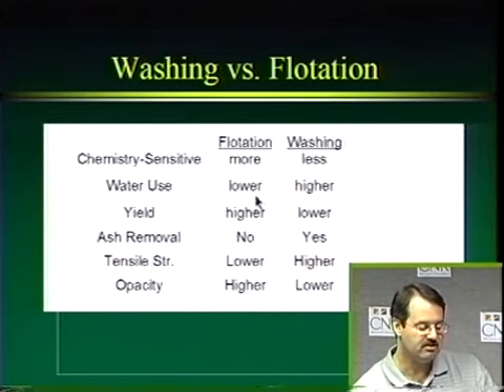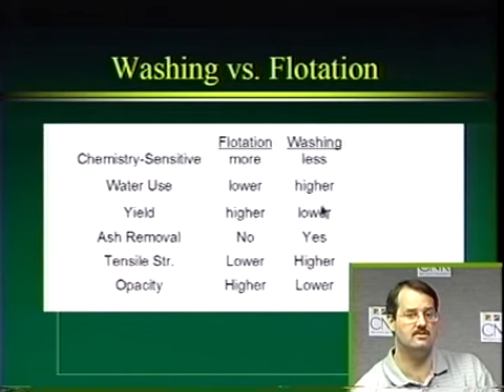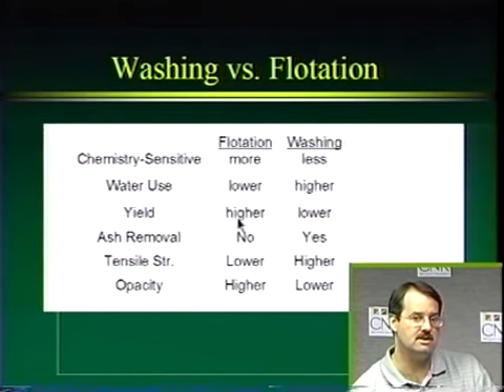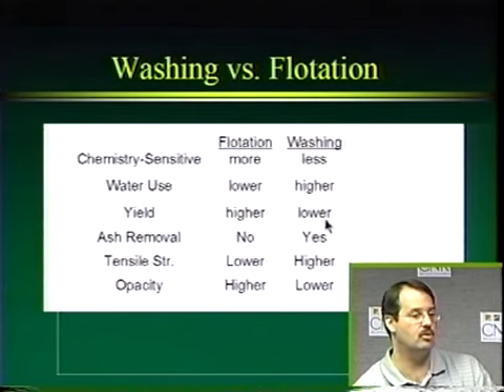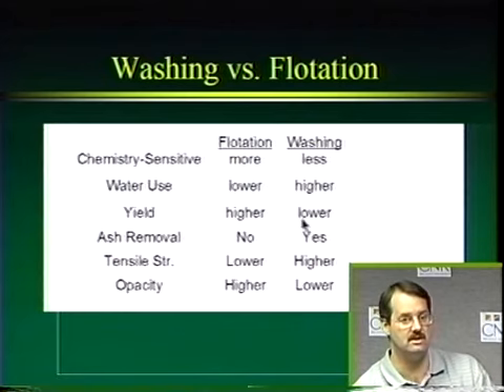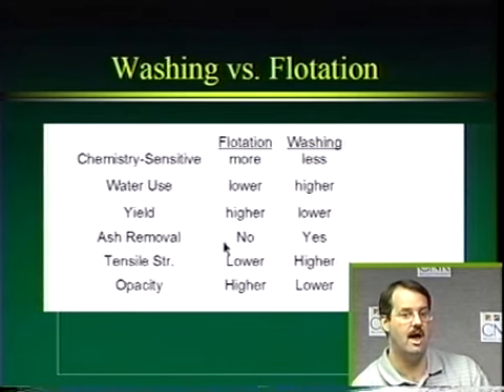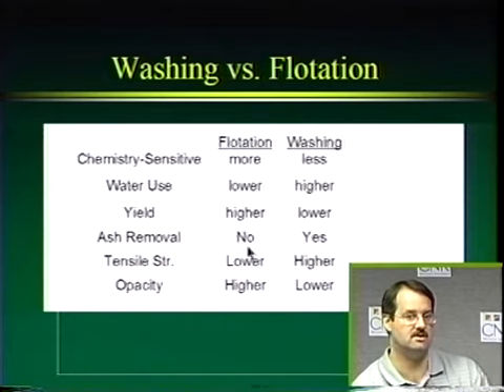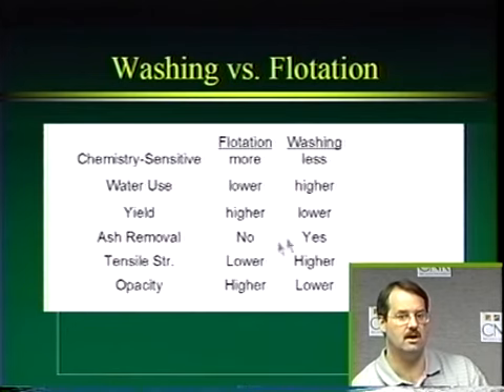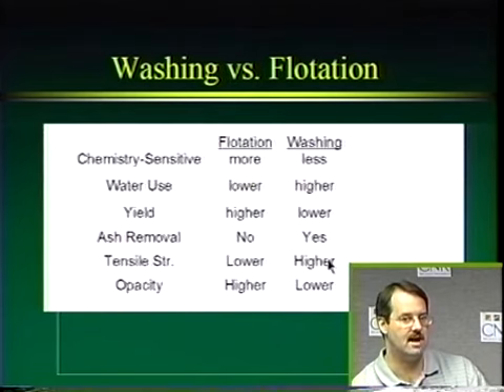Yield. Flotation usually has a higher yield than does washing. And the basic reason is that in flotation, we can retain a lot of our small particles. Small fines and filler can be retained in flotation. However, in washing, we're going to lose a lot of ash, a lot of filler, a lot of fines. So for that reason, washing has lower yield. Okay? Ash removal. In flotation, we're not going to remove a lot of ash. In washing, yes, we are, just like I said before. Tensile strength. Flotation is going to be lower. Washing is going to be higher. Why is that? Well, it's because we're removing a lot of ash in our washing.